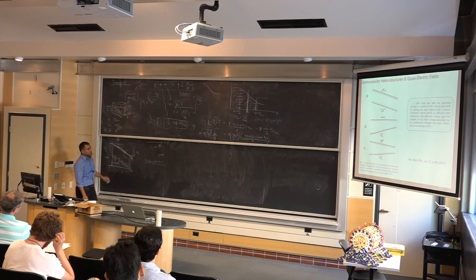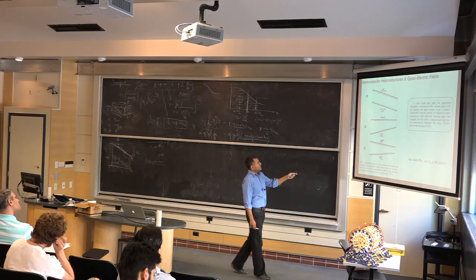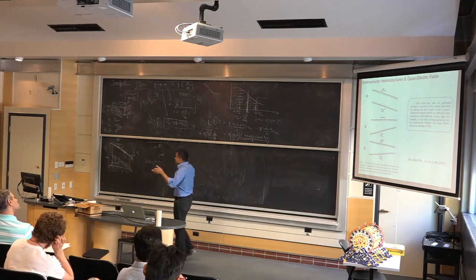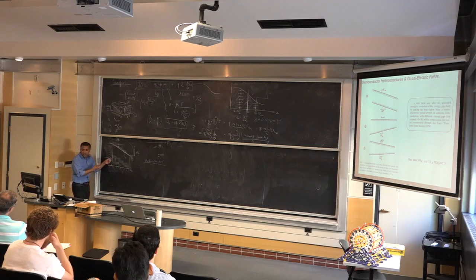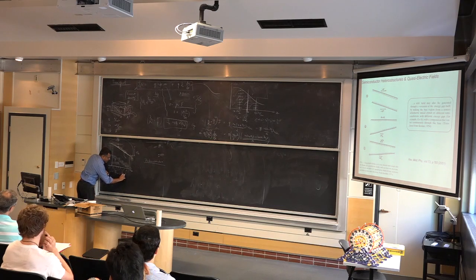So you have broken some sort of very intrinsic symmetry in the material, and you can flip this around. You can make it not possible for electrons to move, whereas the holes can move, right? So this sort of a field, there's no external field in this material. Right? This field is born out of the atoms of the material itself. It's called a quasi-electric field. Again, this is just a name,